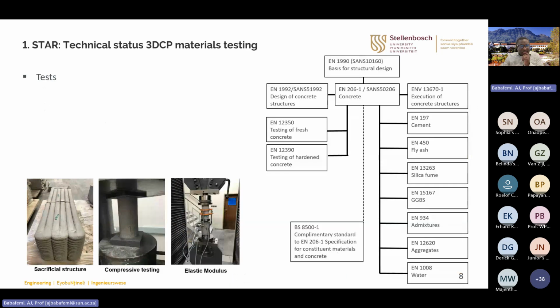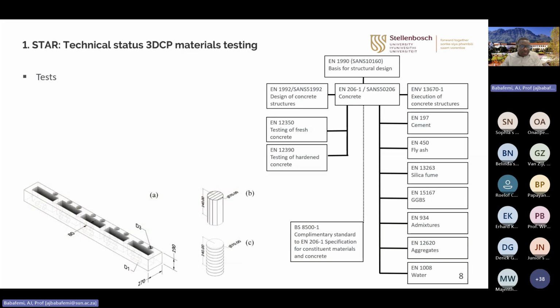So moving on to testing, typically, concrete codes are not only restricted to design models and rules, but of course they refer to standard tests for concrete in terms of the fresh state, hardening properties, or properties in structures, and then some specifications. As you can see, our SANS code is definitely adopting the EU code. And typically with our tests, we print a sacrificial sample from which we can core out samples for compression tests and then elastic modulus.